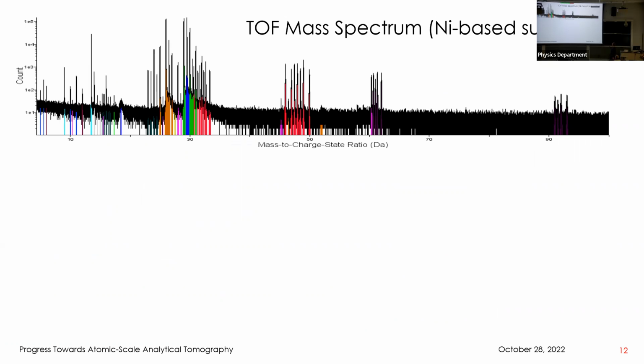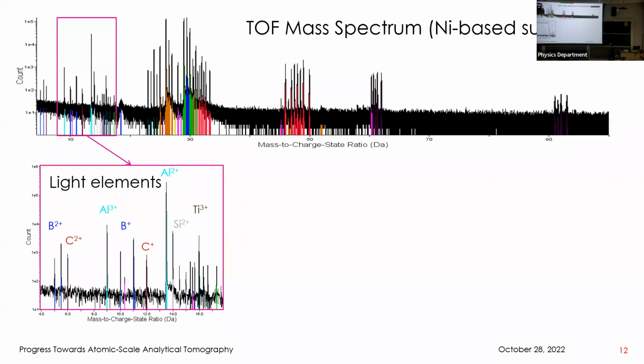Here is a typical mass spectrum from that image I showed earlier. You might see there's a lot of peaks there, but actually they're all generally very well resolved. Notice this is a logarithmic intensity scale here. So this peak is 5 orders of magnitude above background. It makes this a very high signal to noise ratio technique, so you can get to high sensitivities. Atom probe will deliver 10 parts per million sensitivity for most elements, depending on the situation.